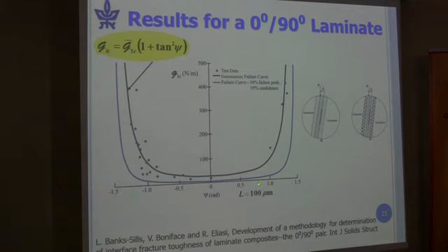And so this is the failure curve, and you choose L to center the data about 0. That's the first choice of L. And then you choose L if you refine it in order to get the best fit that you can between the data and the failure curve. And let me just say that looking at this curve, we have a lot of confidence in it. And the reason we have confidence is these points, which are far out, and this is far out in mode 2, agree very well with the curve. It's near the curve. And this was our G1C bar, which was 26.2.